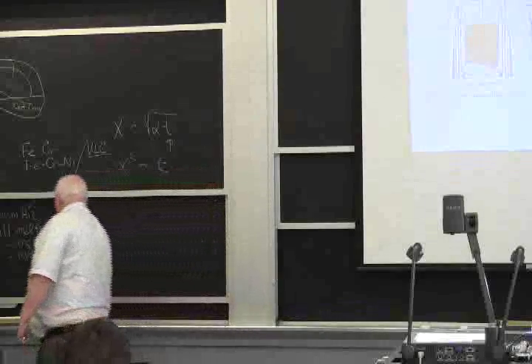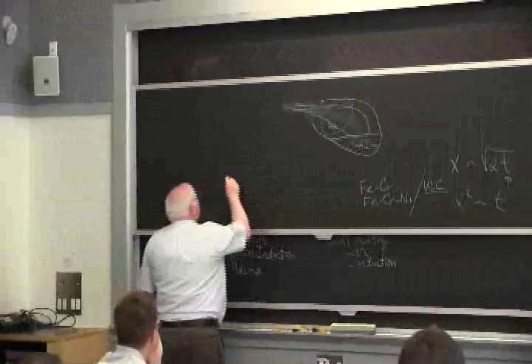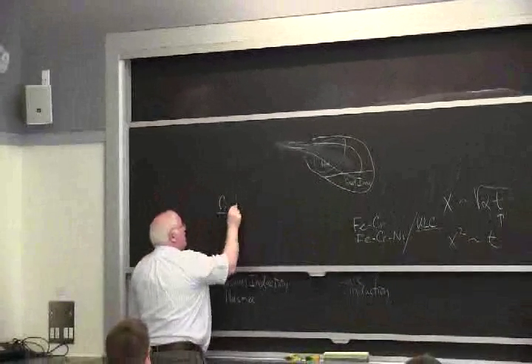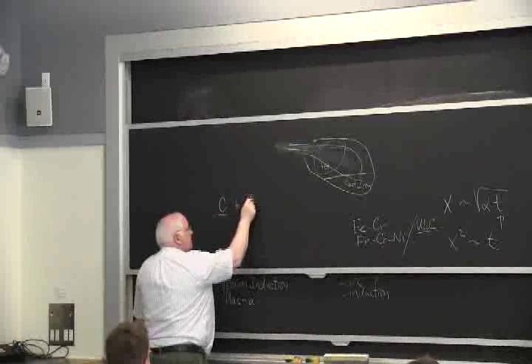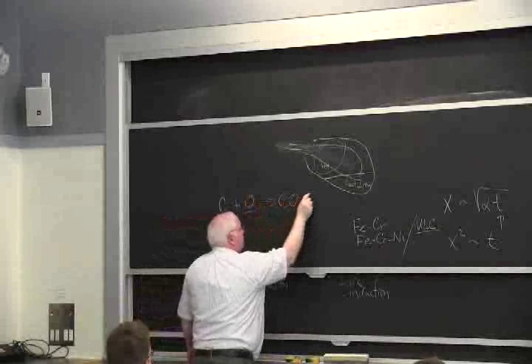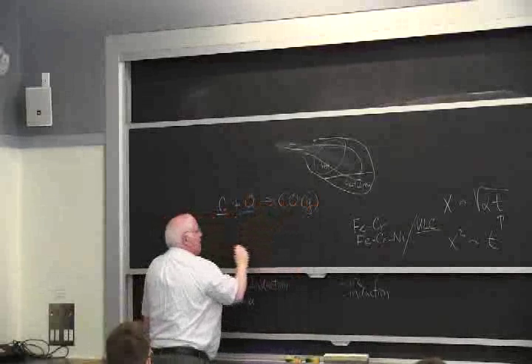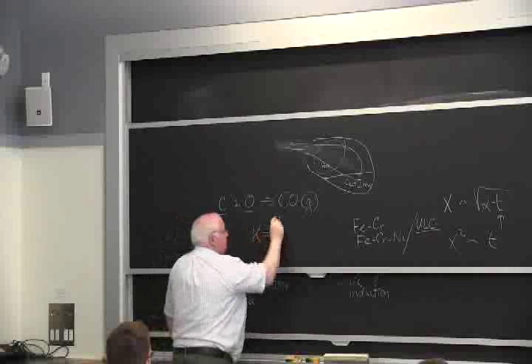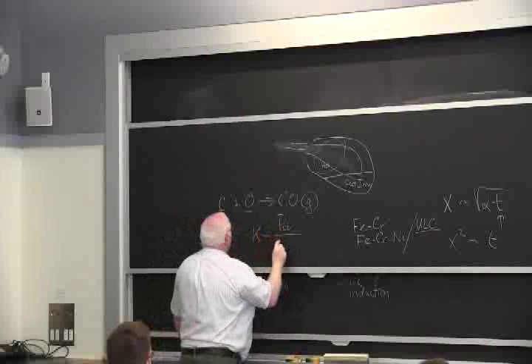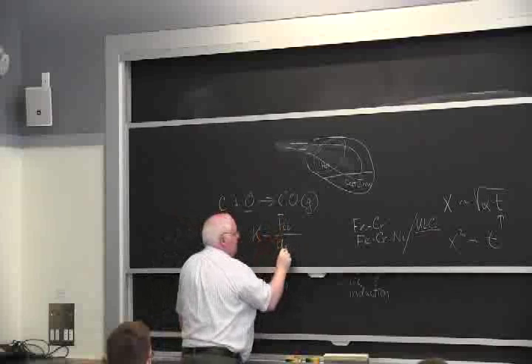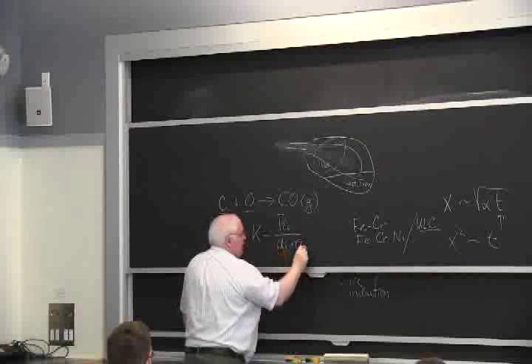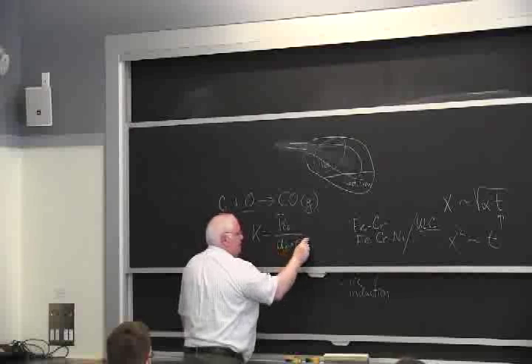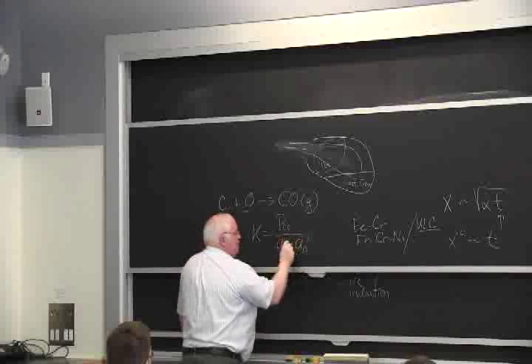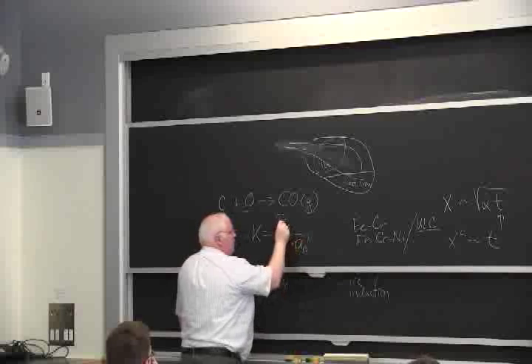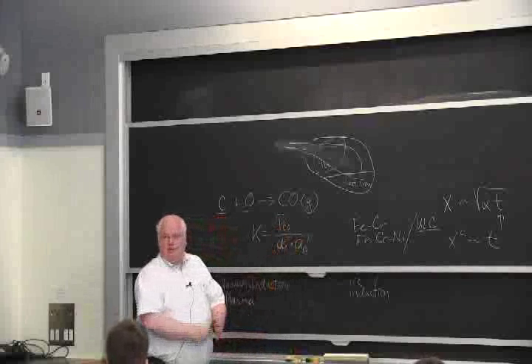The simple reaction, for those of you that are chemists, is carbon, and we put an underline for dissolved in the steel, plus oxygen dissolved in the steel, goes to carbon monoxide gas, and the equilibrium constant of that is the pressure of CO gas divided by the activity of the carbon times the activity of the oxygen. You want to drive this down as low towards 0 as you can. You actually want to drive both of these down towards 0, but in order to do that, you have to have a low CO pressure.